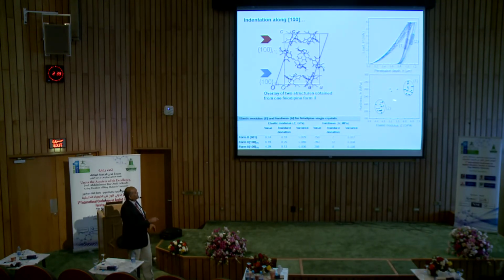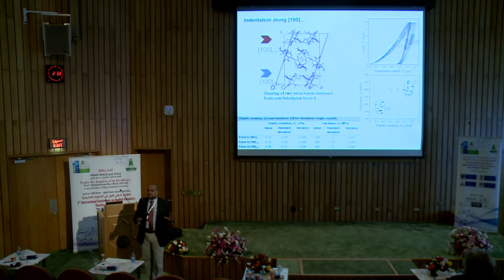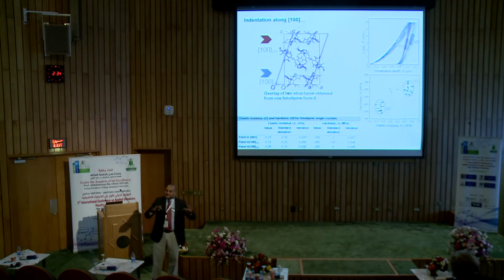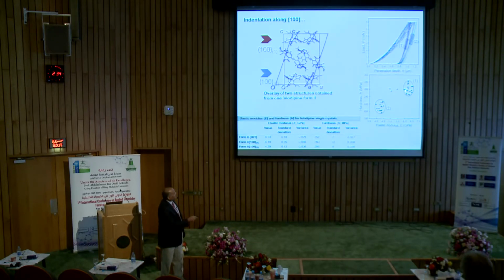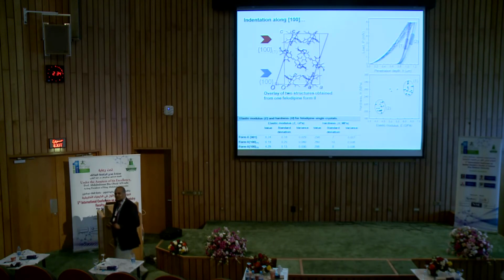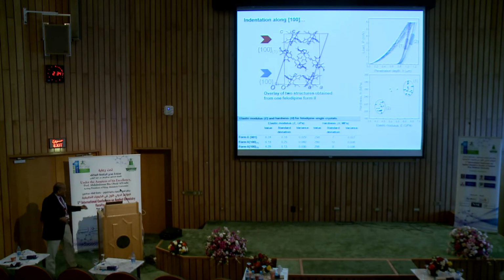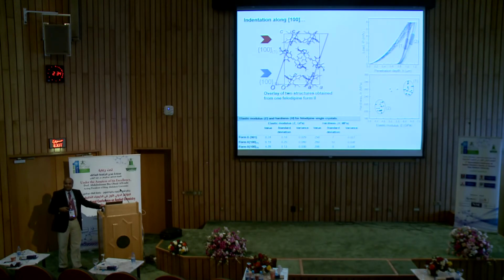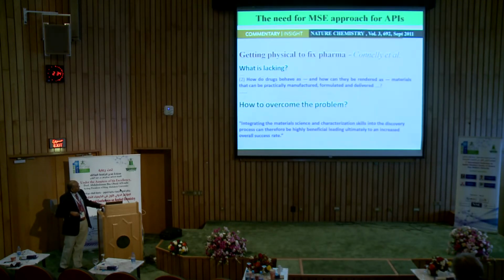So this experiment right away tells me that, if I didn't have that, there is actually a microstructure to the material. All right. There are two different domains, one which has high hardness and modulus, one which has low modulus and hardness. So at a much finer resolution, this is what we anticipated and we saw this. So this allows us to essentially examine the microstructure of material. This is published in Angewandte Chemie this year or last year.